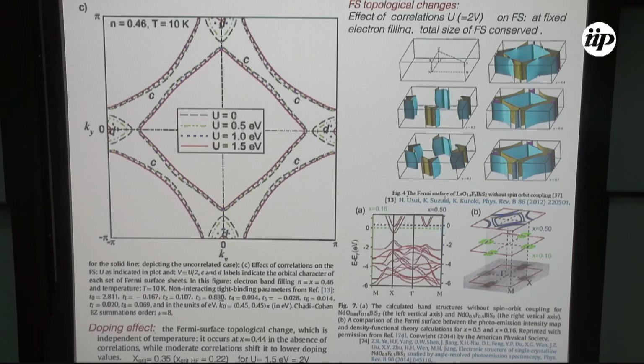This is the calculation by Usui. This is the calculation by another group, Ye and other people, from 2014. They did also the band structure calculations and the Fermi surface. And again, this is for neodymium, also with 50% doping. And you see that something quite similar happens. So you have, for smaller dopings, this kind of smaller Fermi surface. And then at some point, you have a transition to this larger Fermi surface. So that's a feature which is common.